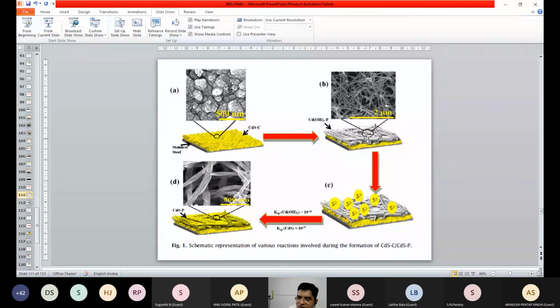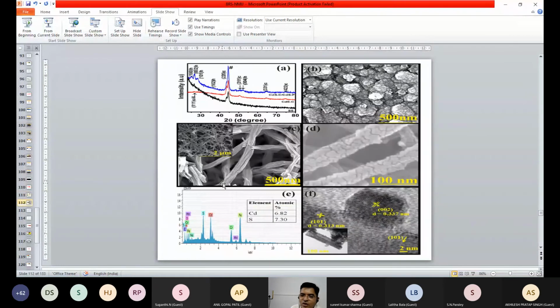So hydroxide gets replaced by sulfur, so that at the end we can see that these are the cadmium sulfide nanowires. This is porous cadmium sulfide nanowire, right? And here you can see the X-ray diffraction pattern. This is CdS deposited on stainless steel, and this is a cadmium sulfide nanowire. And this is an HRTEM analysis, and it has a very high surface area.